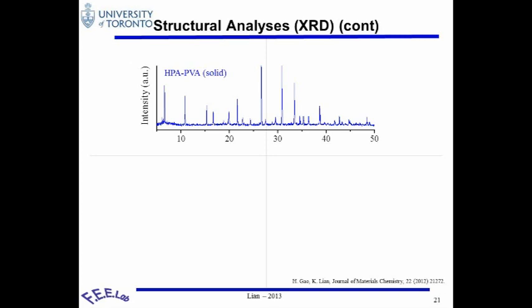As one thing we know, the most important thing in our HPA, heteropoly acid, is the crystal, the water, or with PVA is the water retention, because the proton does transfer over the water, and the reason we saw the Nafion's performance deteriorated is due to the water retention problem. So we actually looked at XRD and tried to identify the best way to monitor or trace the water content.